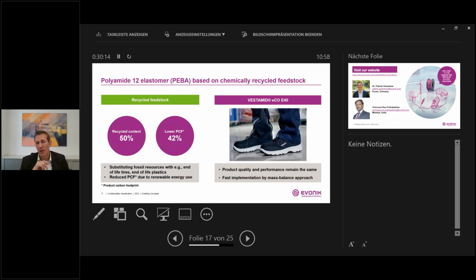Important to mention is that we are also using renewable energy to produce those polyamide elastomers. And these materials are then used, for instance, in such shoes. So in general, the quality is absolutely identical to the quality of the fossil polyamide 12 elastomers. However, the product carbon footprint is lowered and the recycled content is significantly increased. And with this, I would love to end my presentation.